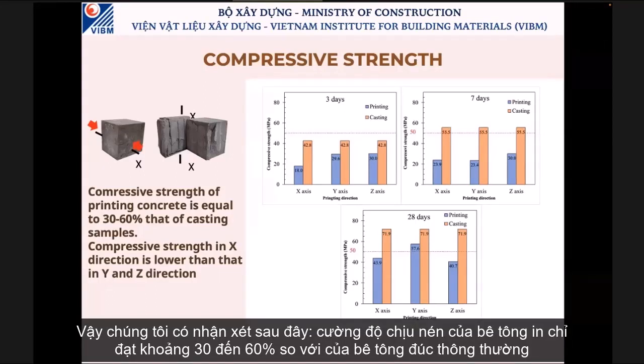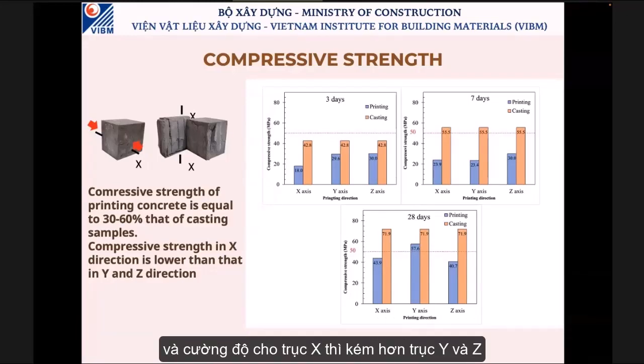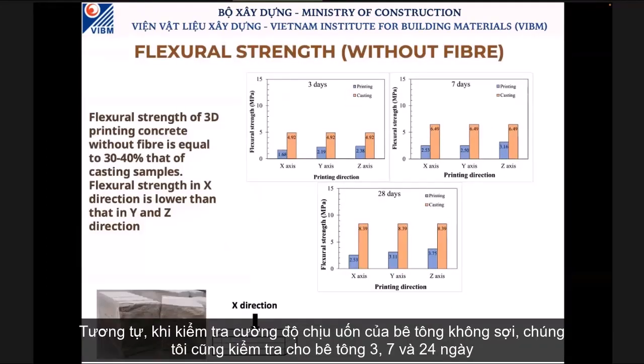So the comment here is on the compressive strength of printed concrete. We found it varies from 30 to 60% of that of cast specimens, and the compressive strength in the X direction is lower than that in the Y and Z directions. Quite a similar ratio in the test results with flexural strength.